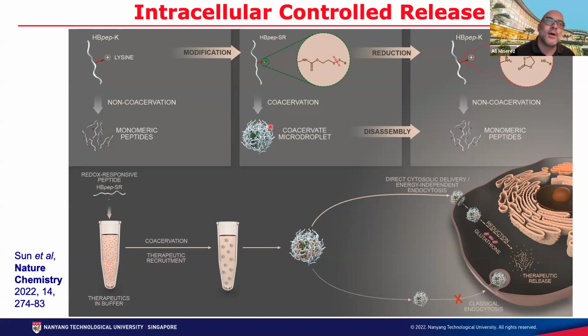And if you induce this coacervation in the presence of therapeutics, which are in solution, then the therapeutic will get entrapped inside the droplet. And then this droplet, that is shown here, enters the cell through a process which is not the classical way that things usually go inside the cell. It gets reduced, and then spontaneously it disassembles, and it delivers the payload. And so it's very powerful because any macromolecule in solution here, as long as it goes inside the droplet, can be delivered.